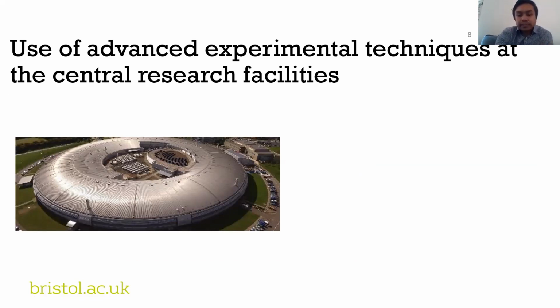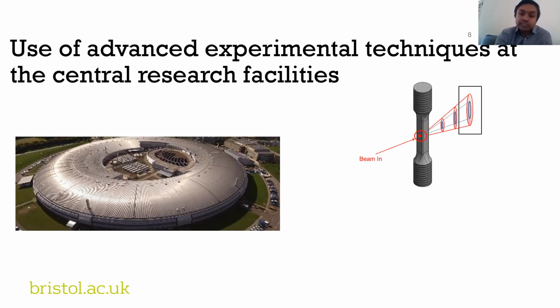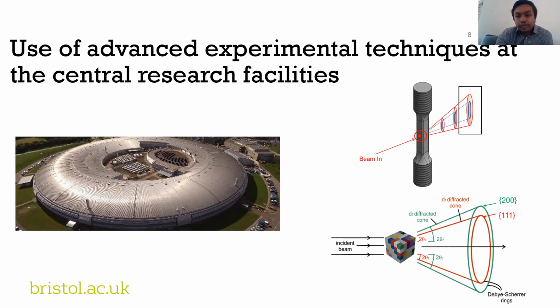And what these techniques offer is very high energy X-ray or neutron, which can penetrate through the material. For example, this small sample can give you the information of the deformation of your grain with respect to their orientation and how those are related to the loading axis of my sample. So this gives us a really amazing and unique way to compare our model's prediction of local deformation of how grains are deforming to experimental observation of the local deformation.